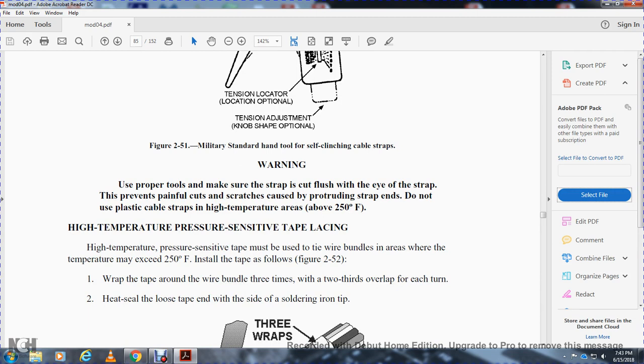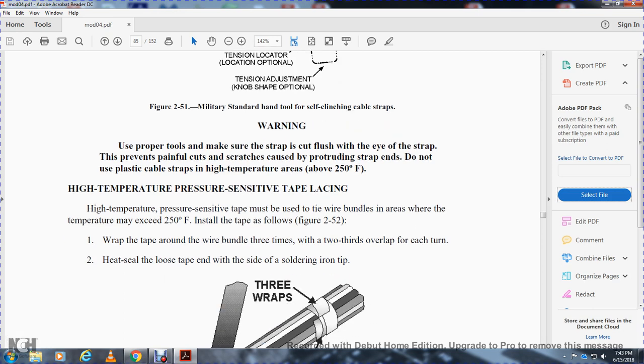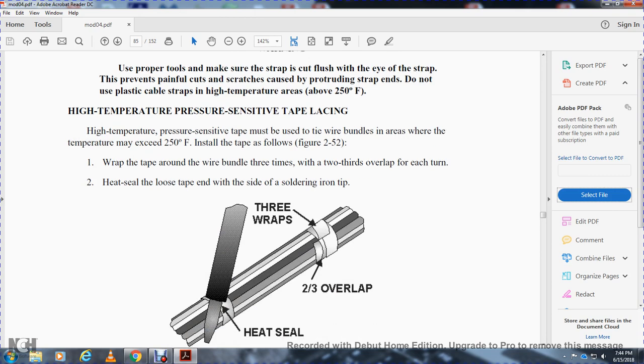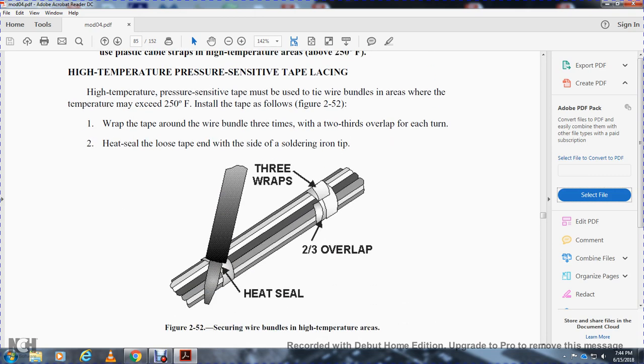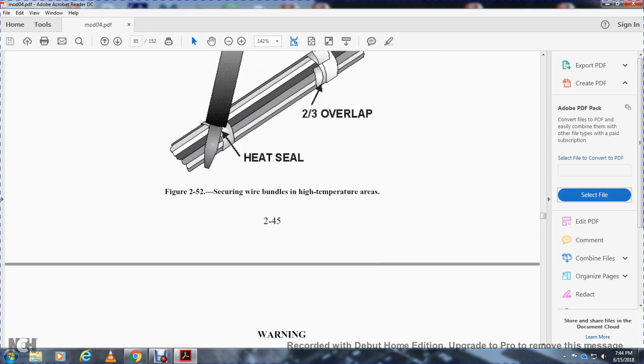High temperature pressure sensitive tape lacing. High temperature pressure sensitive tape must be used to tie wire bundles in areas where the temperature exceeds 250 degrees Fahrenheit. Install the tape as shown in Figure 2-52. Wrap the tape around the wire bundles 3 times with 2/3 overlap. In turn, heat seal the loose tape on the end of the side over a soldering iron tip. 3 wraps, 2/3 overlap, heat seal. Tying the wire bundles in high temperature areas.